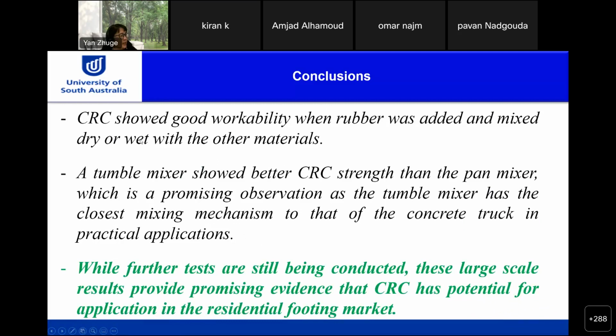So as a summary, CRC shows good workability when rubber was added and mixed dry and wet with other materials. A tumble mixer showed better CRC strength than the pan mix, which is a promising observation, as the tumble mixer has a closest mixing mechanism similar to the concrete truck in practical applications. So while further testing is still being conducted, these large-scale results provide promising evidence that crumb rubber concrete has potential for application in the residential footing market.